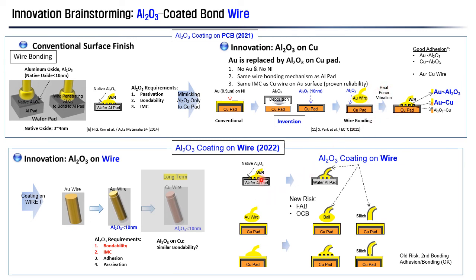You're seeing a gold wire bonded to the aluminum pad. We introduced aluminum oxide coating on bond wire. There's no interference. And you're seeing a conventional bond wire bonded to the PCB copper pad. Here's the aluminum oxide coating. There's no interference. Looking at the second bonding, there's no interference as well. The only new risk coming in as we introduced aluminum oxide coated bond wire would be a free air ball formation and OCB because of the fact that a bond wire is completely surrounded by the aluminum oxide coating. That's what I'm going to talk about in the next slide.